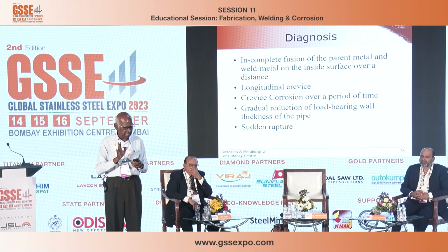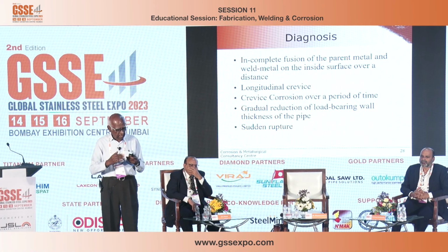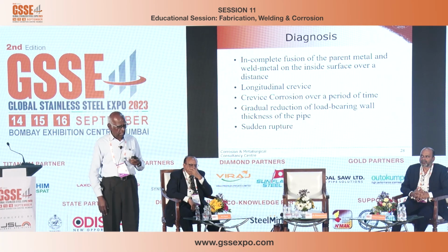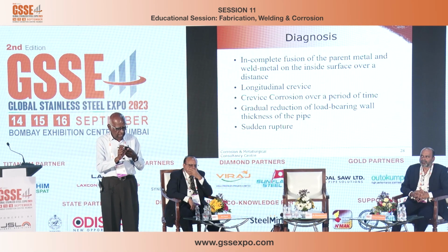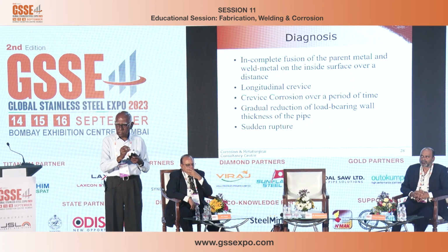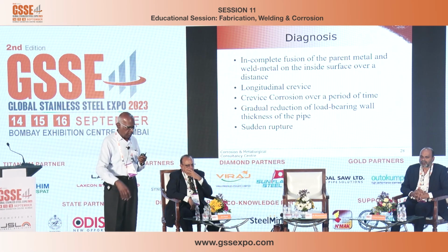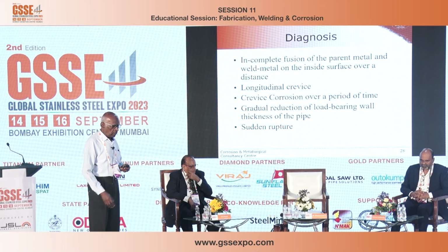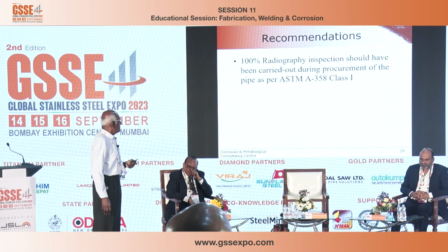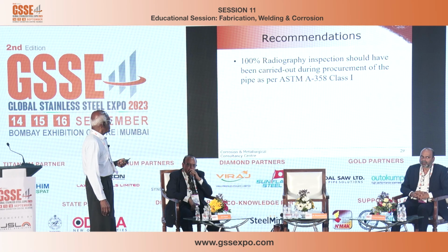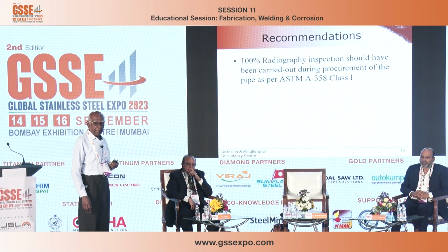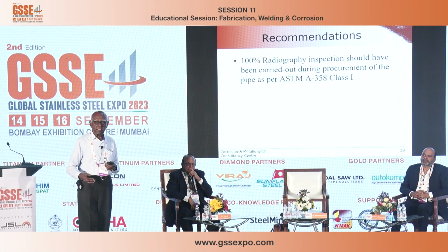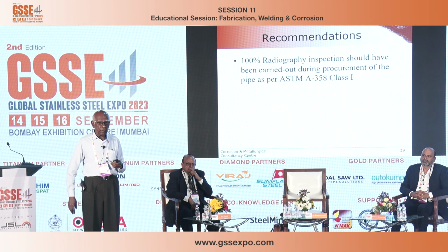That's a form of corrosion. We don't want to go into the detail. There are several forms of corrosion, out of which crevice corrosion, over a period of only a few months, gradually reduced the load-bearing wall thickness at that particular location. It became a balloon, so it was a sudden rupture. This should have been avoided by proper radiographic inspection during procurement of the pipe. The radiography inspection is to check the soundness of the weld. The pipe may be qualified, but not the weld joint.